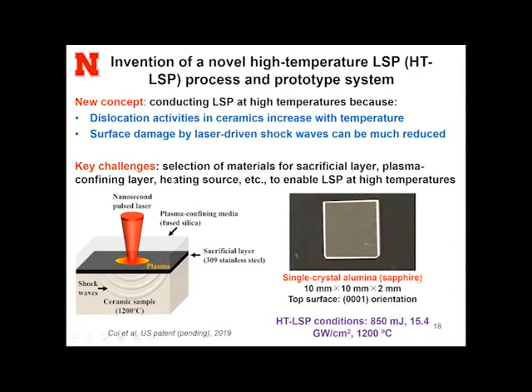So this is the idea, but when we performed the work, we found the key challenge is the system, because now we cannot use water as a plasma confining media, we cannot use the setup we use for room temperature. So we have spent a lot of effort to select materials suitable for high temperature for the sacrificial layer, plasma confining layer, and the heating source. So finally, we invented our prototype system and filed a patent.